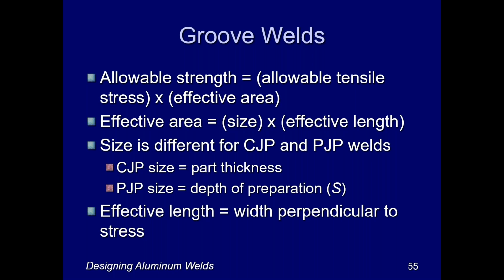If we have complete joint penetration, the size of the weld is the full thickness of the part. If we don't have CJP, we have PJP, partial joint penetration, then the size of the weld is going to be equal to the depth of preparation, or in other words, the depth of that groove that you saw in that sample weld above. And the effective length is just the width perpendicular to the direction of stress.